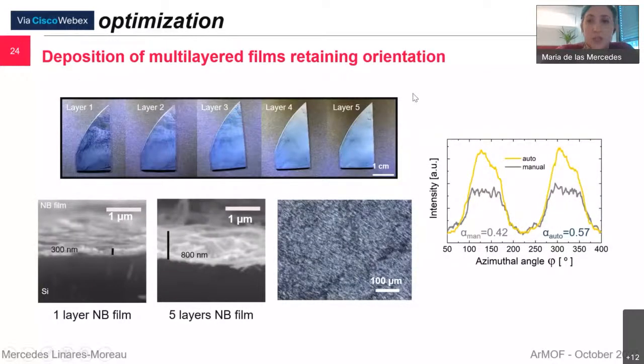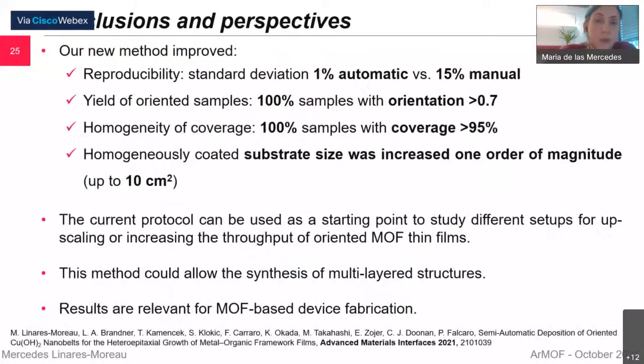And also this method allows for the deposition of multi-layered films that still maintain the orientation. So in this example, 5 layers of nanobelts are deposited one after the other, and it requires a control that you cannot have with the manual procedure.